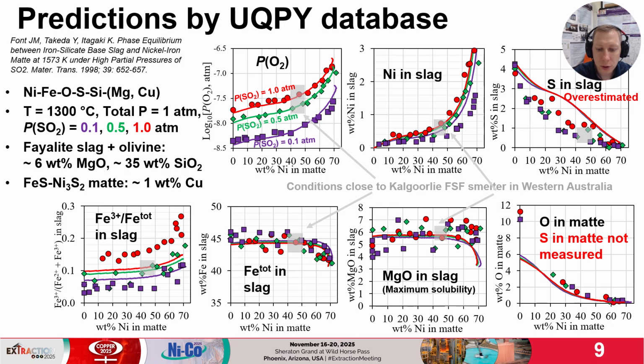Oxygen partial pressure increases as expected, and it is higher for high SO2 conditions. The chemical solubility of nickel in slag increases.